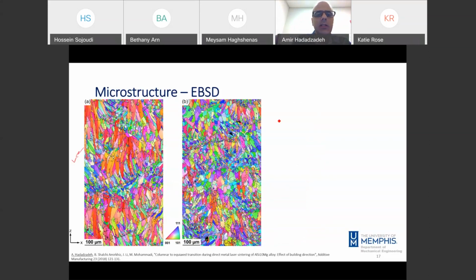In the case of the vertical sample, on the left-hand side, this is vertical, this is horizontal, the majority of grains are columnar grains, while in the horizontal sample, we have a bimodal structure, and I can say most of the grains are equiaxed. And that is because of the change in the thermal boundary conditions and the thermal history experienced by the material. So that's a general answer to this question. But if you really need more details, this is our paper in Additive. You can take a look at that paper. I have used a solidification model to elaborate on how this kind of microstructure evolves in the material.